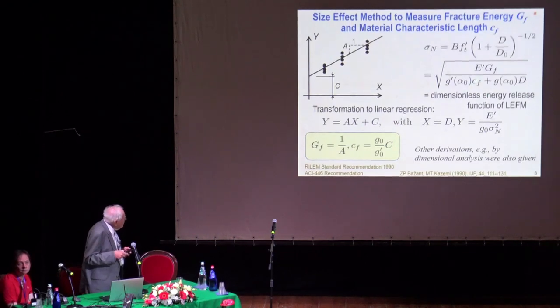Now, this formula, luckily, can be converted easily to linear regression, where Y is the inverse of strength squared, X is simply D, that gives a linear line, and linear regression is, of course, the easiest case for statistics, which gives all the statistical information.